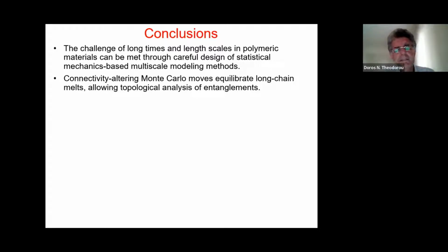If one cuts and pastes chains, always observing the rules of the Monte Carlo, one can equilibrate the long length scale conformational properties of chains in a melt many orders of magnitude faster than, say, with molecular dynamics. And one can then take these well-equilibrated configurations and subject them to topological analysis to learn about entanglements.